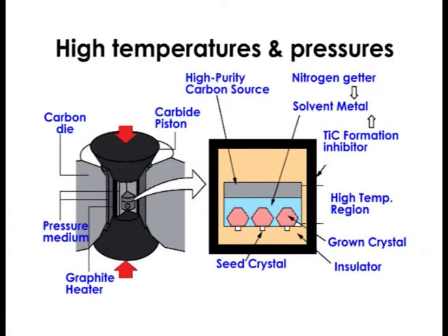After the solidified metallic mass of the cartridge and its contents is removed from the press, it is crushed and the diamonds are extracted by dissolving away the non-diamond content with acids. The second method of diamond synthesis is CVD diamond synthesis.